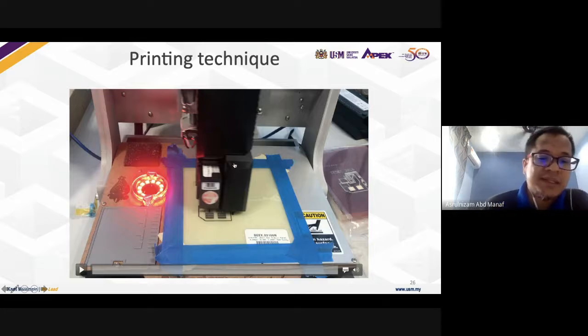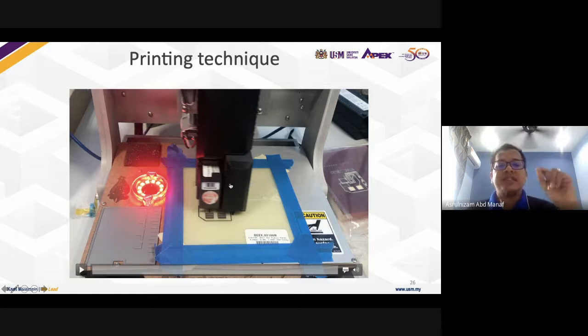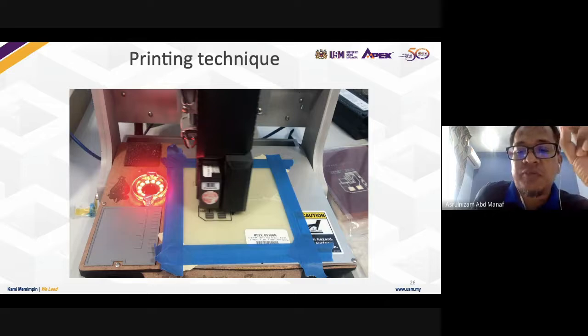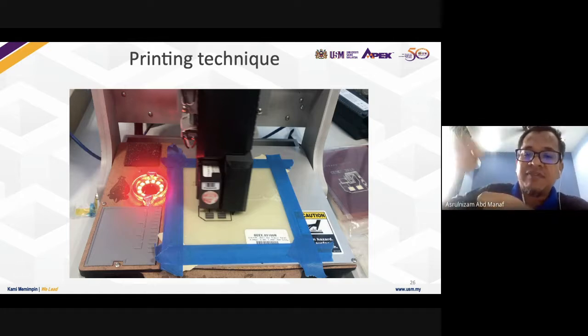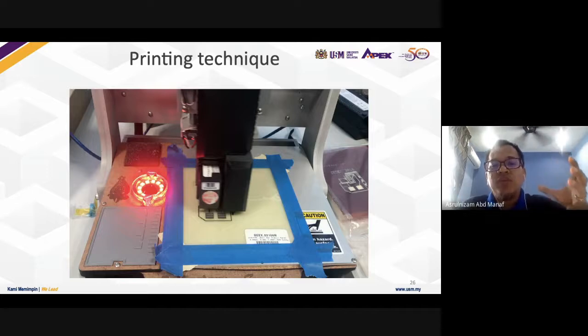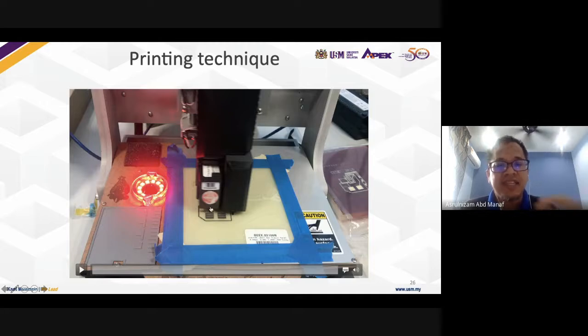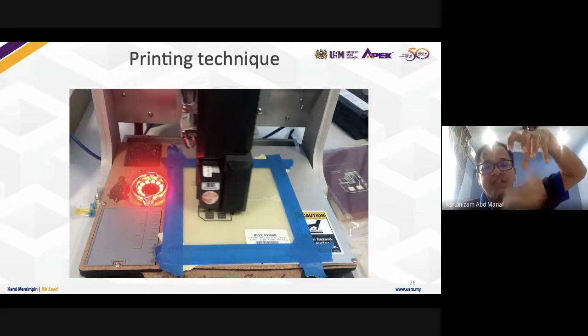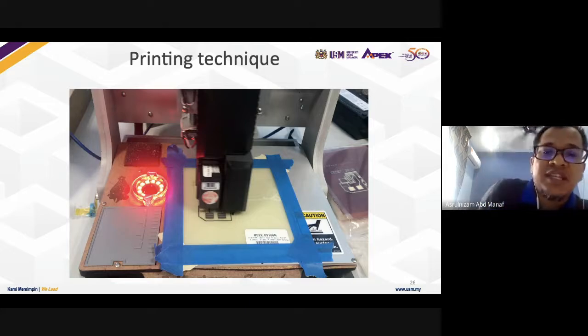For the inkjet based printer, the critical thing is the viscosity. It means you cannot use a paste, right? And then there are nozzles. If you just want to print silver, it should be fine. But if you want to tailor-make your ink to be a polymer that must be conductive, you have to add particles, the silver flake. Because of that, we have to tailor-make in terms of the nozzles, because the nozzle can clog. That is the first problem we face.